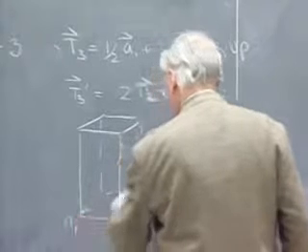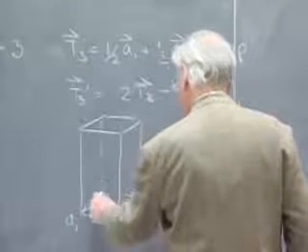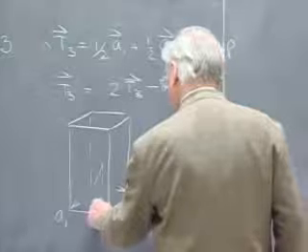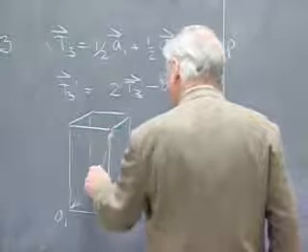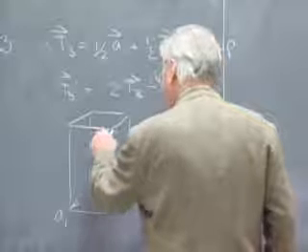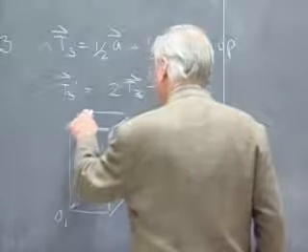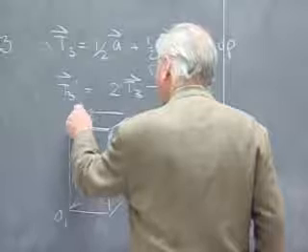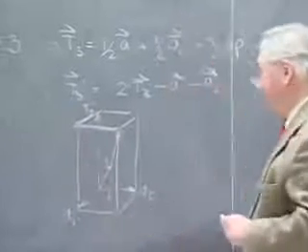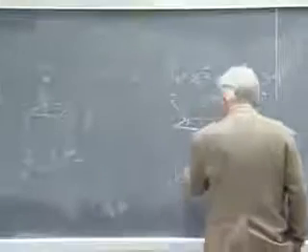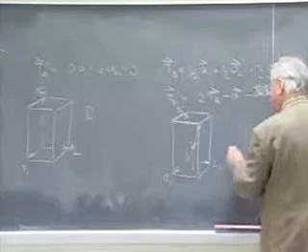with A1 and A2. And now the translation that went up directly over the center of the base of the net below, twice that minus A2 minus A1 brings you back to a third translation, T3 prime, that's normal to the base. So both cells have the same shape. This is a primitive. This is a body-centered tetragonal lattice.